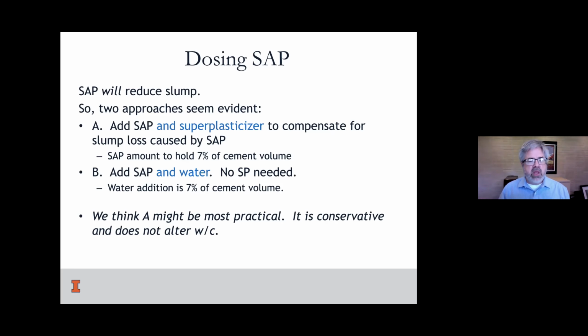Secondly, B, we could add some extra water. And therefore, we would want to have a mix design that understood that. And because of this mix design, we're going to change the water cement ratio if we do that. We would maybe avoid the use of the superplasticizer, et cetera.